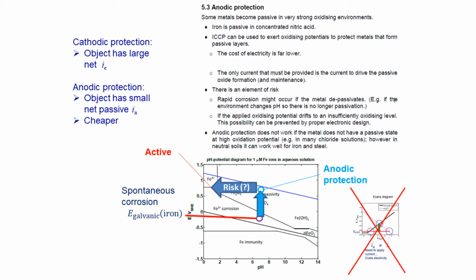Second, as well as a somewhat restricted material selection choice for anodic protection to work, we also have the possibility that there is some risk here. Because we're deliberately applying a positive surface potential, so long as the metal remains in an environment with, say, a pH and a low chloride level which is compatible with the material staying passive, then anodic protection will indeed make it passive. But if we have some environmental shift, for example the pH becomes a lot more acidic in the case of iron, then our applied positive potential might, instead of causing passivity, actually cause severe active corrosion.